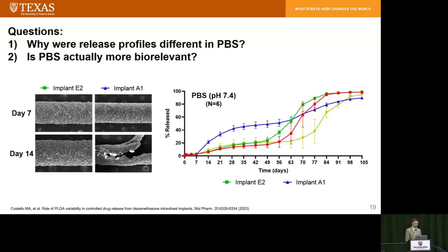Question 1, here's the answer. Looking at implant E2, which had the Evonik material, and implant formulation A1, which had the Kinam material, the A1 formulation had this earlier initial burst release. And the reason why is that the implant physically split open rather than slowly eroding, which is the typical degradation process. So this A1 formulation had this interesting behavior where it split open at an early time point, which we think was due to very minor differences in the residual monomer content of the PLGA used there. So then question 2, is this methodology actually more biorelevant, or is it overly discriminatory?